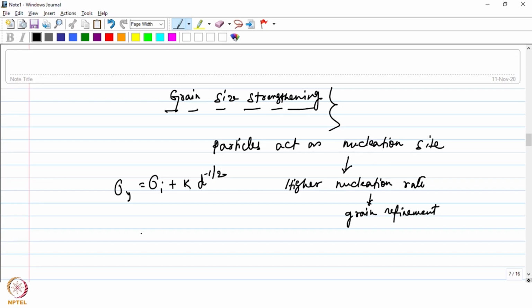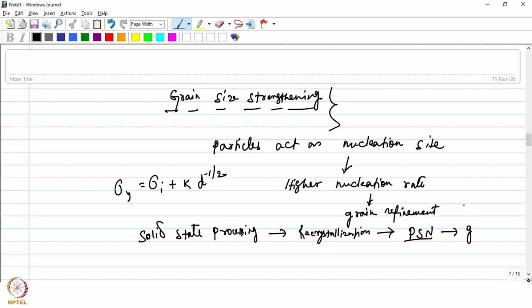And in fact, this can happen during solid state processing also, when recrystallization can occur, and particles above a given critical size can actually stimulate the nucleation of the strain-free grains during the recrystallization process. So that particle stimulated nucleation, or PSN in short, can give rise to a finer grain size.